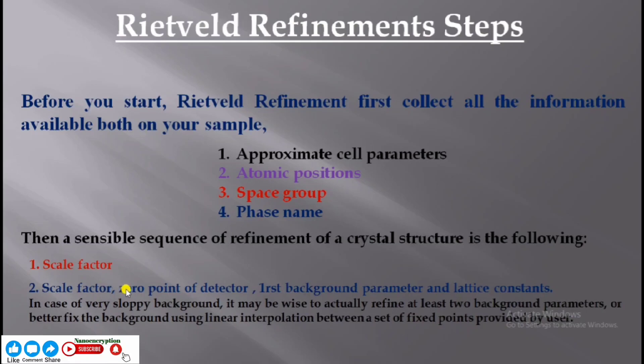First, refine the Scale Factor. Second, refine the Scale Factor Zero Point, then the first Background Parameter, and then the Lattice Parameters.